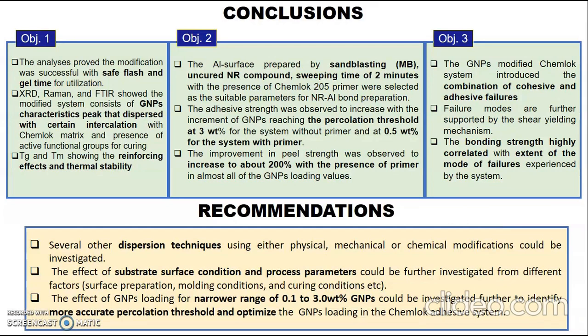To conclude, objective 1 is achieved as the analysis made shows safe flash time and gel time for utilization. The structural analysis also proved the GNP presence in the modified Chemlok adhesive system. Both TG and TM show good thermal stability. Objective 2 is achieved as mechanical blasting and uncured natural rubber with 2 minute sweeping time were selected as suitable process parameters. Adhesive strength increased as GNP loading increased until reaching a certain percolation threshold at 3 weight% for the system without primer and 0.5 weight% for the system with primer. The improvement in peel strength was observed to increase to about 200% with the presence of primer, and objective 3 is achieved as the bonding strength is highly correlated with the extent of failure mode.